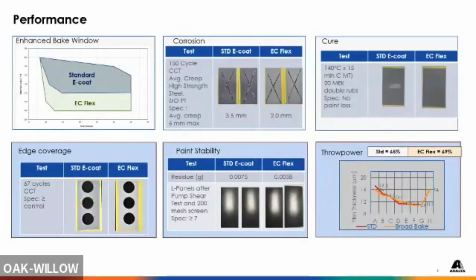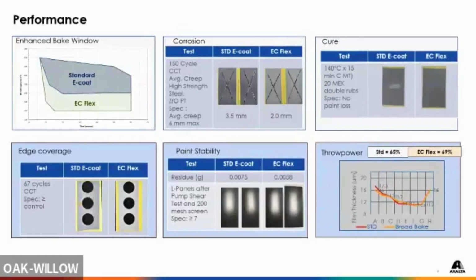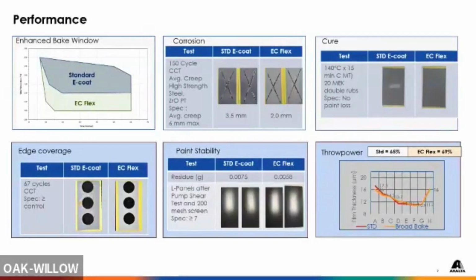So in the middle, we just want to make sure under extreme stress, agitation, heat, does any of that stuff fall out of solution? Back in the 80s and 90s, things used to fall out of solution quite a bit. Usually it's pigment, so that technology has come a long way. But this is just a confirmation. So you put this under stress, you do an L panel, and you run it through a filter and you measure how much residue you actually capture in the filtered media.